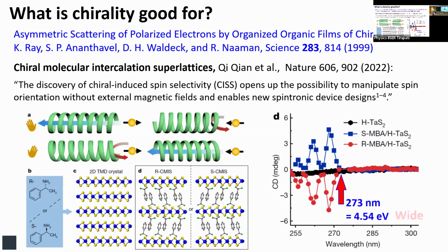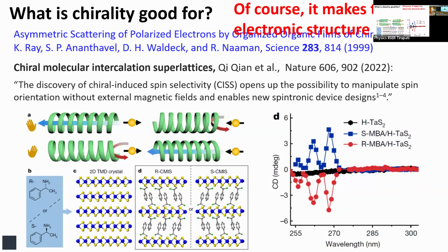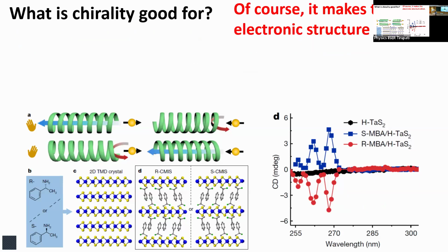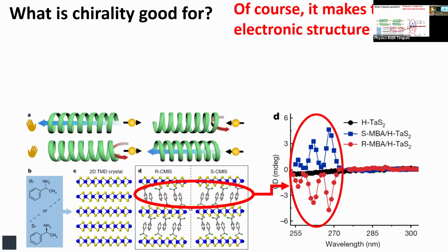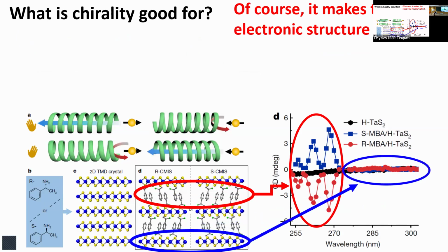Good. Then one asks, is it chiral only at this part and not at that part? That part also is tantalum disulfide absorbing there. It has electronic states way down, and only very high energy states are chiral. Why is that? When we ask the question, this chirality that you're seeing here actually is because of absorption from these molecules. These have their electronic states here. The inorganic part has not only electronic states here, but also here, and there's absolutely no chirality transfer.